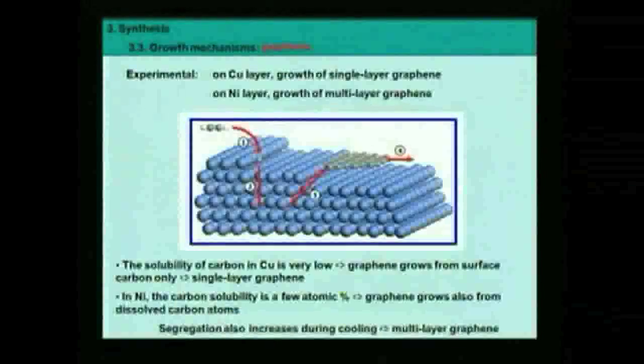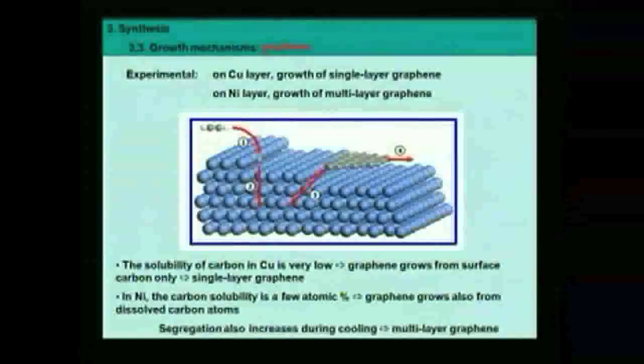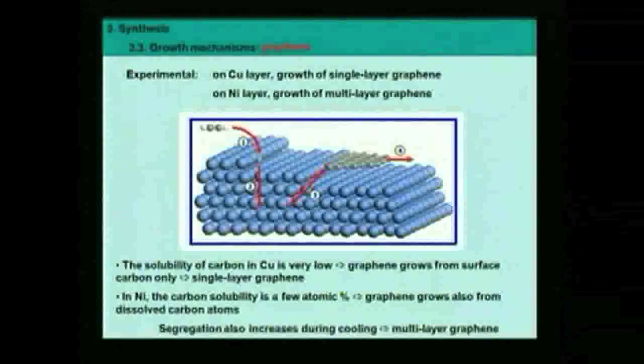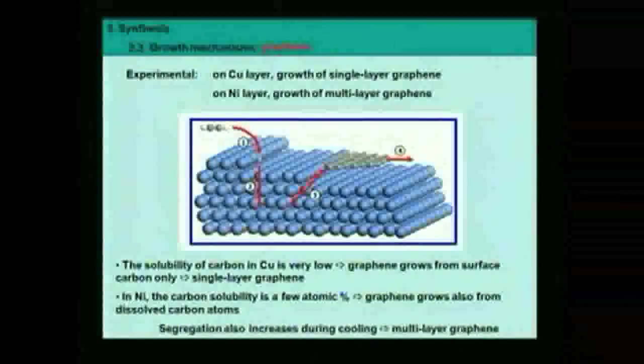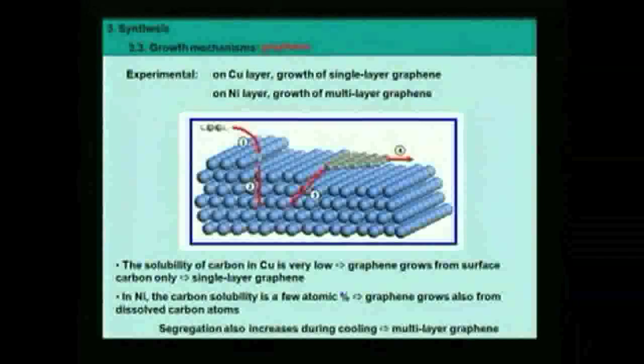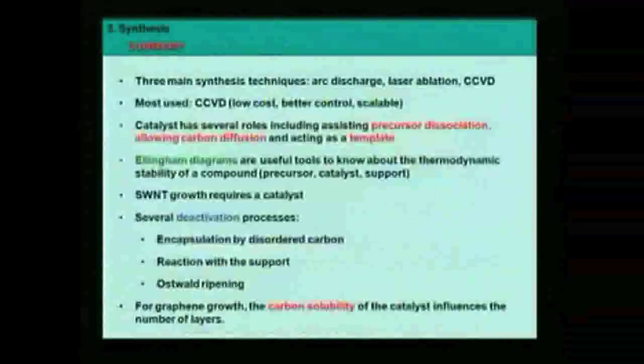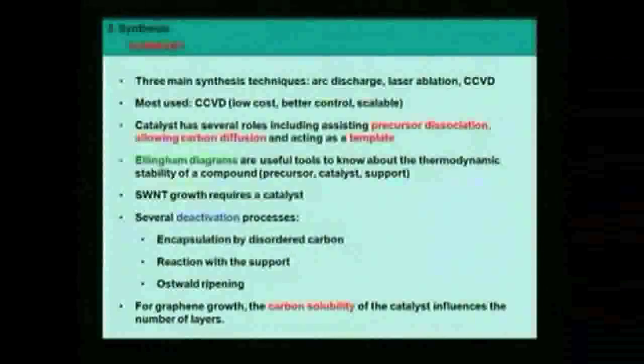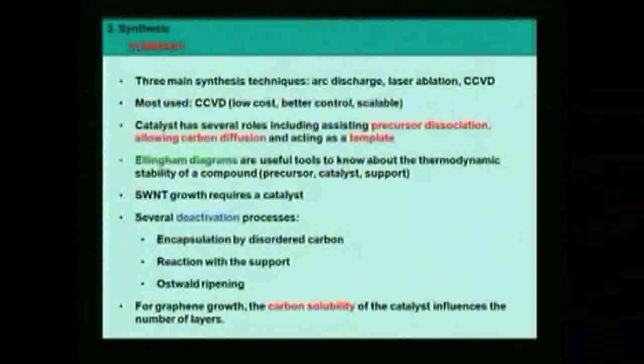Okay, for graphene, I will not talk about that because I have not enough time, but it's a question of dissolution. The solubility of carbon is also an important characteristic of a good catalyst. If you dissolve too much carbon, then during cooling, the carbon will segregate and you will form new graphene layers. Okay, this is a summary of what I said here. It's no use that I read it. You will have the slides and you can read them afterwards.